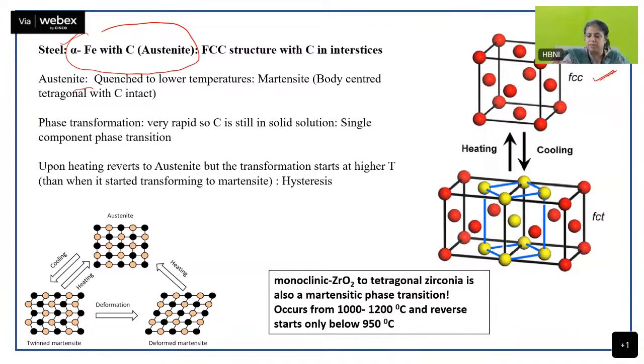Okay. So what happens is now when you cool it, it becomes tetragonal, and we talked about this earlier also. Now this will have a smaller volume than the cubic unit cell. So the phase transition happens from FCC to body centered tetragonal. Okay, but it happens just by slight movement of the atoms, and hence it is called a martensitic transition. This is a martensite phase. This is an austenite phase.